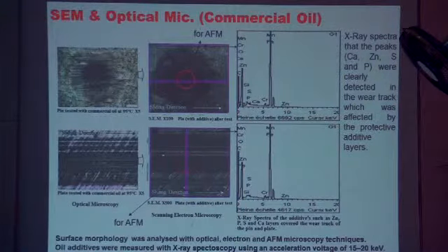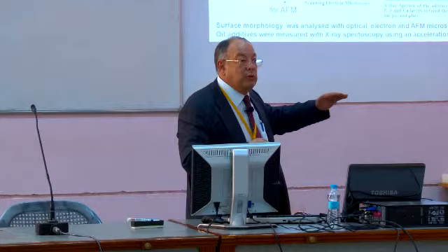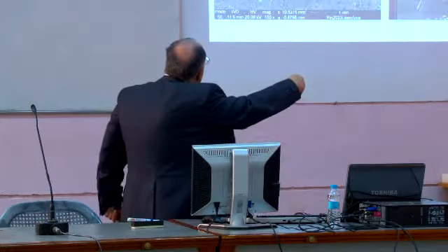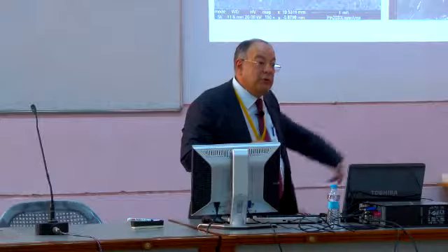And at that time, we found layers on the pin and plate because we used the same material. The material wasn't different that time, but now even the plate and the pin played a role to form a protective layer on the surface. You see, this is much more darker because the surface is well degraded and has well-formed layers on the surface.